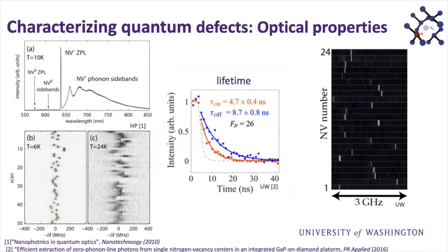And so then the next thing, so that's the spin properties. The next thing is the optical properties. And what I mentioned before is that we want the photons that each defect emits to be spectrally identical. If we look at this photoluminescent spectra of the nitrogen vacancy center, we see this very, very sharp peak. And we may naively assume that at least for these 3% of the photons that are emitted into this sharp transition, they would be identical. And unfortunately for the nitrogen vacancy center, this broadband emission out here is phonon assisted, and it turns out to be not useful.